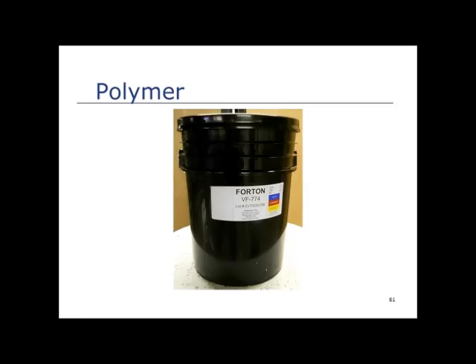Set time? Basically, yes. It's still concrete. It still sets about the same rate, but you're not fighting set time, you're fighting drying time. So it's something always to be aware of. You're fighting the polymer losing moisture, the concrete losing moisture, and that gives the illusion it's setting up, but really bad things are happening because you're losing moisture.